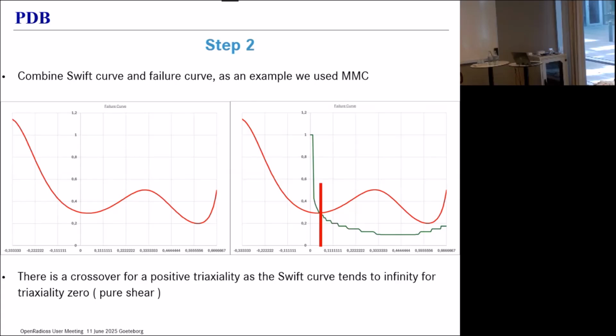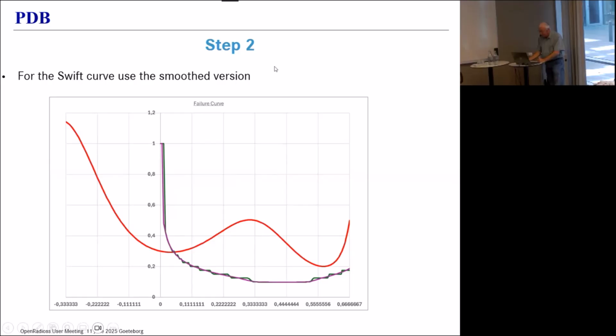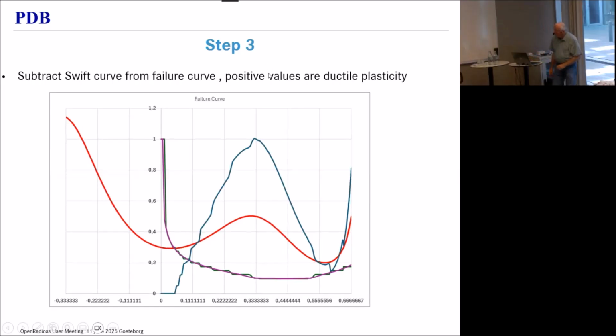Well, as long as the instability curve is above the failure curve, we don't have to regularize, so we're fine. When the failure curve is above the instability curve, we have to regularize. So we're gonna subtract one from the other. And we've done that here. Obviously, the value of that subtraction is 0 in the intersection point. And when we get a negative, we set it to 0. Sometimes we have two intersection points. There could be a second intersection point here in the neighborhood of equibiaxial tension. That did not happen for this particular material.